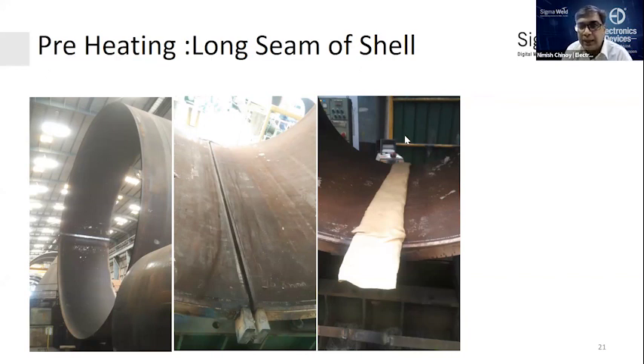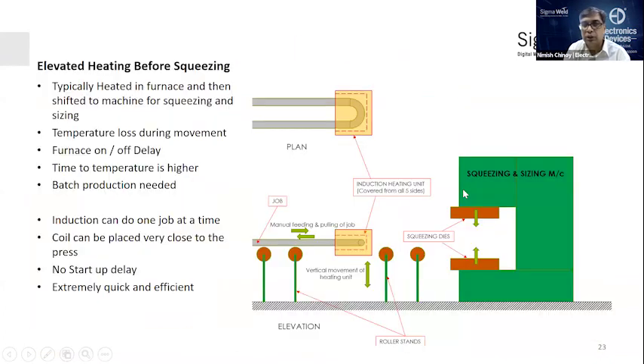Here we have made a blanket within which the induction coil is placed. You can place the blanket on top of the job. It takes about 2 minutes to do so. Press start. In about 20-25 minutes, the temperature is achieved. Remove the blanket and start welding. You save close to 3 to 4 hours of your cycle time. That means you can produce much faster on the shop floor.